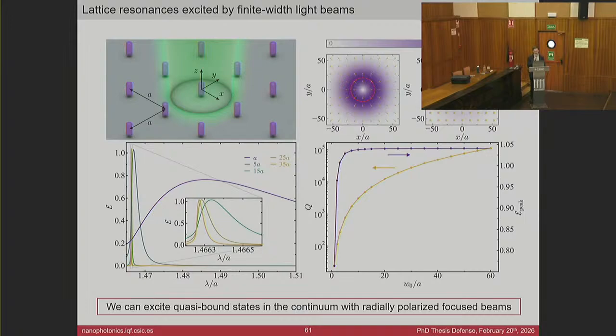Yes, that is one of the ideas behind this approximation. Basically, what it consists of is that this green tensor, which will include all the interaction within the nanostructure, we just keep at first the part that doesn't depend on frequency, which we identify with the quasi-static limit. And then, assuming that the distribution of the polarization density in our material is constant, which is an approximation, we can use the other fields that we have first neglected inside the green tensor to correct our polarizability, something like this.